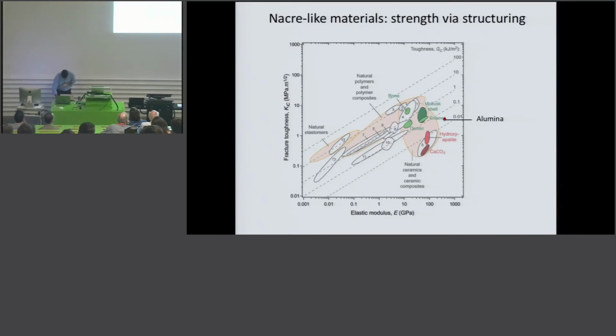So to that, and that's when you have a fracture mode. So the very last part, what we've been able to do is, if we look back into the Ashby plot that I showed in the beginning, we started off with an alumina platelet, which is much stronger than calcium carbonate, and through structuring, we've been able to increase its properties by a factor of 3 or 4, beating basically the properties of nacre itself, so we're stronger than the seashell itself.